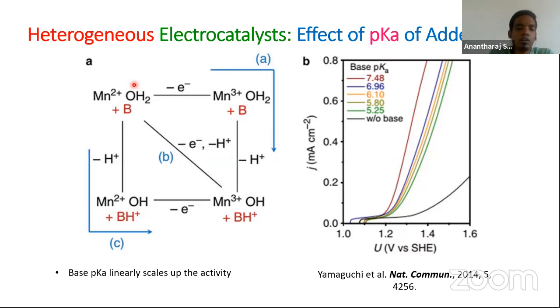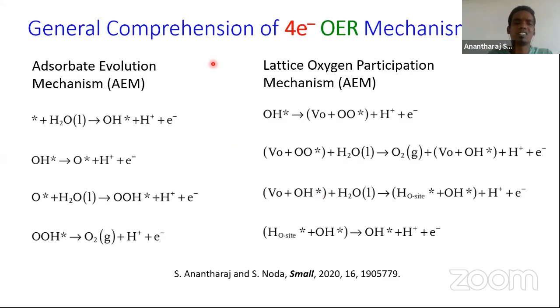So people have found that adding a base could trigger this conversion in a concerted fashion. And they also studied the pKa of the added base could also increase the activity, just like the amount of base. So when the pKa is very high, you can see very high activity and lowering in overpotential. So these are all very important findings made in this area. So I chose to share with you all. And it is the time to see the mechanisms. Because I told, because of the energy efficiency concern, OER and HER are usually done in acid and alkaline solution. And in the case of acid and alkaline solution, the general comprehension as of now for 4-electron OER is either this or this.